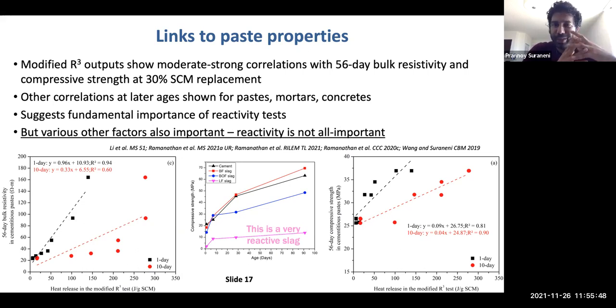So this is why you simply cannot link a reactivity test to concrete properties because, for example, we've seen materials which have phosphorus pentoxide, which, again, they're reactive, but this retards cement hydration. We've seen materials with high amounts of alkali or LOI, which are reactive, but ultimately they do somewhat reduce the cement strength in some cases.